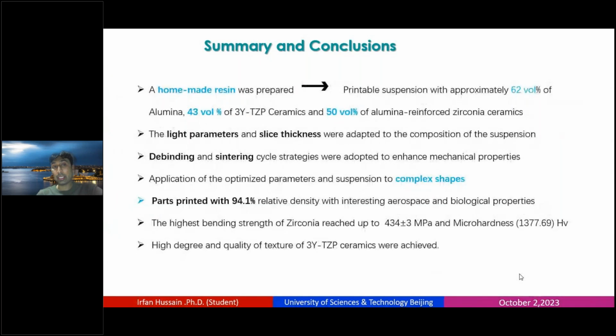So also the last slide, summary and conclusion. I have used homemade resin that was prepared. For the printable suspension, approximately for the case of alumina, I have used 62% volume alumina, and for yttria-stabilized zirconia 43% volume ceramic, and for alumina-reinforced the solid content was a maximum of 50% volume.